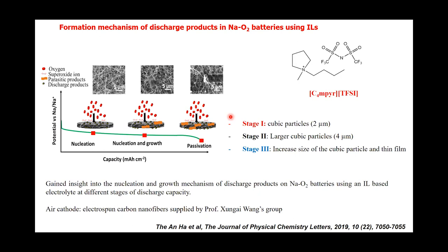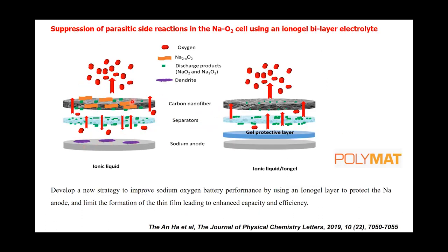So we conclude that during battery performance with ionic liquid, besides the discharge product, sodium peroxide and superoxide generation, some byproduct forms on the air cathode, and that's the reason why it limits the capacity and cycling. So next work, I collaborated with the polymer group to develop a new strategy to improve battery performance. We use the ion gel to protect the anode, and this results in limiting the thin film byproduct, and that's the reason leading to the enhanced capacity and coulombic efficiency.